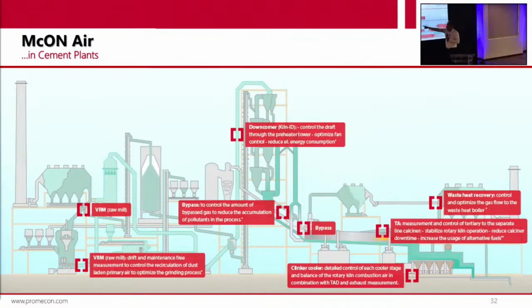That's one of the most common applications we have for Holcim Lafarge. They've done dozens of these. And they all have an O2 measurement down here. So they're both necessary, but it's an optimization to get the process optimized. Then we can measure tertiary air here. So we can measure the total combustion air that goes into your pre-calciner.